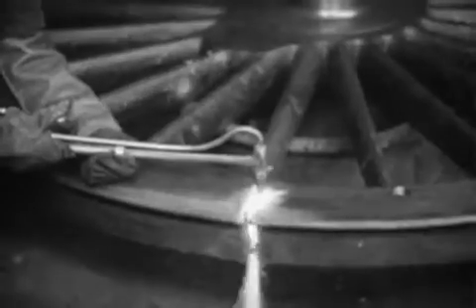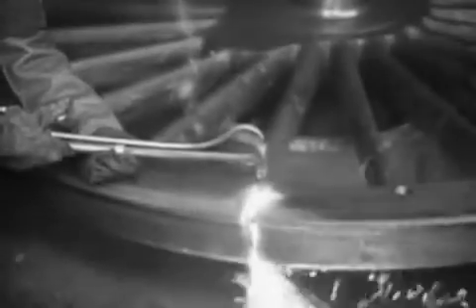The procedure was somewhat as follows. As soon as an examiner finds a flaw in a tire, he reports it to the research department, who send a man to examine it. This representative asks for the flawed section to be cut out. When the first cut is made, the tire, which of course is shrunk onto the wheel center, springs open, and the investigator measures the opening of the cut.